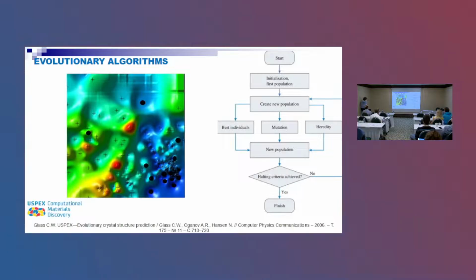So what we did, we decided to look, first of all, at whether we can consider all energy structures. Basically, we say the following: let us take several atoms and predict what kind of structure can exist in this case, considering not only the ground state but the lowest metastable states. So let us put in some volume 5 atoms, 3 of them titanium, 2 of them selenium, and just look at what the energy will be.